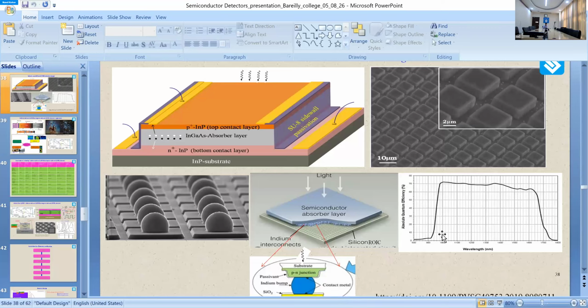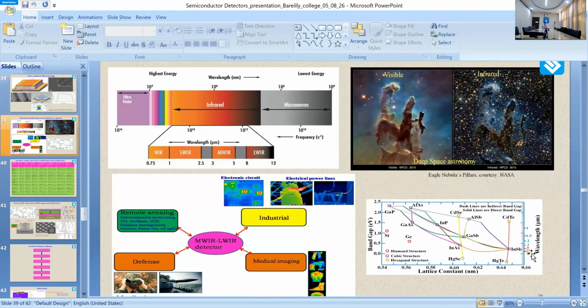So this is a typical quantum efficiency, or responsivity, of indium gallium arsenide on an indium phosphide substrate. The quantum efficiency starts increasing above 1000 nanometer, and it decreases up to 1900 nanometer. So it is very good. It has very good response from 1 micron to around 2 microns. This way it covers from the near infrared to the short wave range of the electromagnetic spectrum. So this is about the near to short wave range.